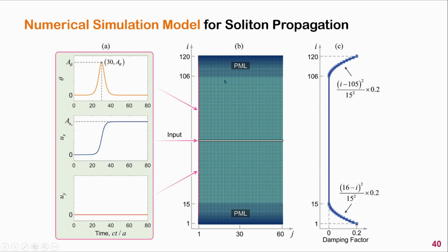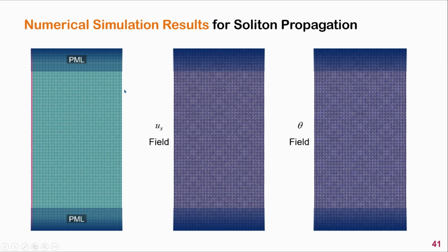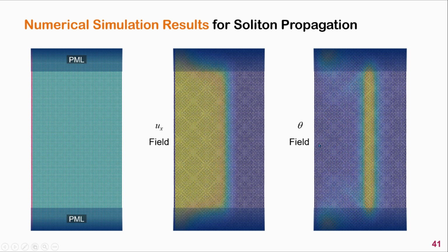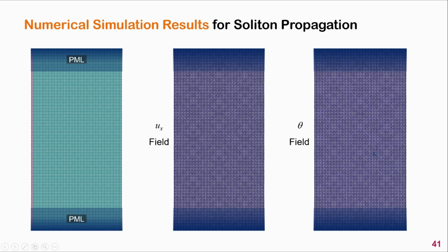In the numerical simulation, the model consists of 120 by 60 units, and the analytically predicted solitary solution is applied as input to the left boundary. To eliminate boundary effects, we apply perfectly matched layers on the top and the bottom boundary, and the distribution of the damping coefficient is illustrated here. As shown by the numerical simulation, the excited wave pulse is propagating stably without distortion.